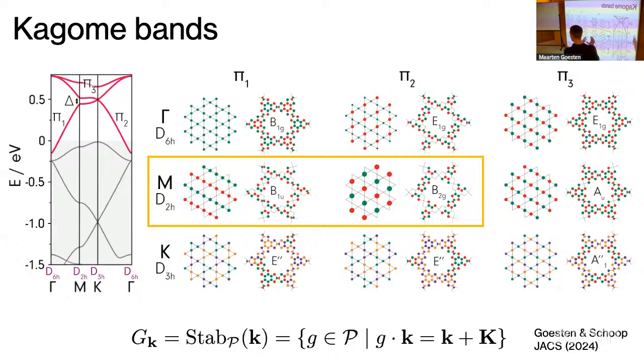You can actually find some MOFs in which the 2D band structure will have a crossing close to the Fermi level. The reason why I'm not so interested in these single layer 2D structures is because I know that they're experimentally very difficult to obtain. And when they obtain them experimentally, usually they grow them on top of a surface. And then the electric field of the surface will actually quash all the topological observables that you have. So it's not so interesting. Although recently they had a paper where they did synthesize such a 2D layer and they did some spectroscopies on that.